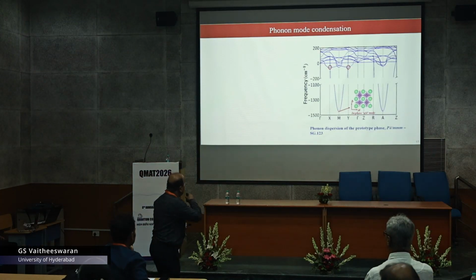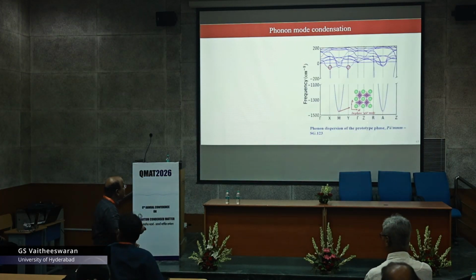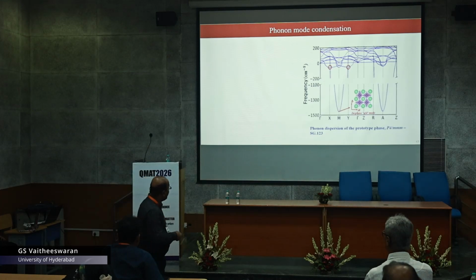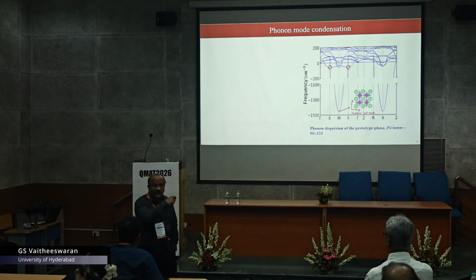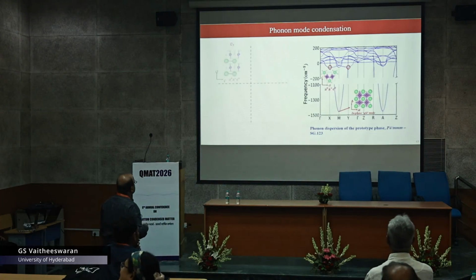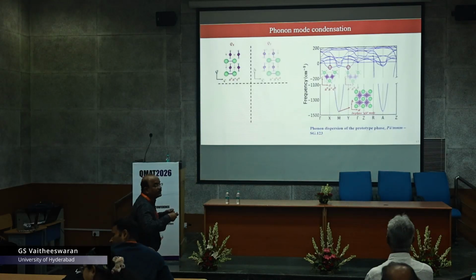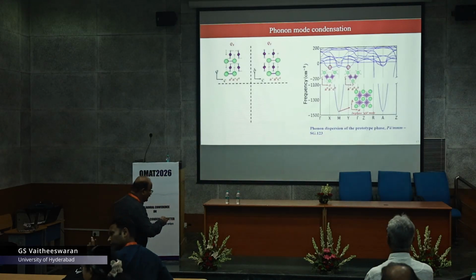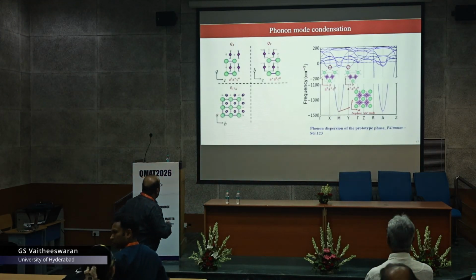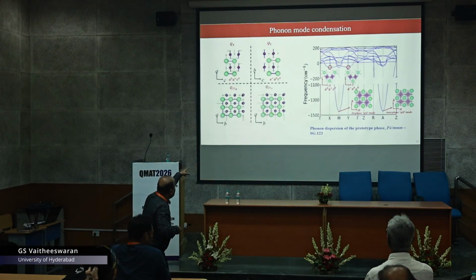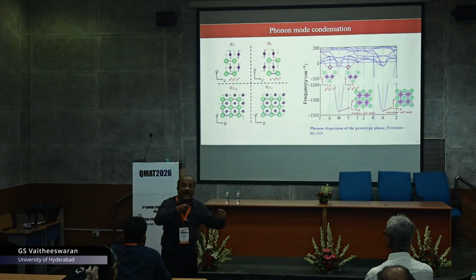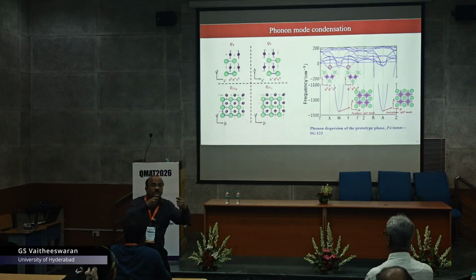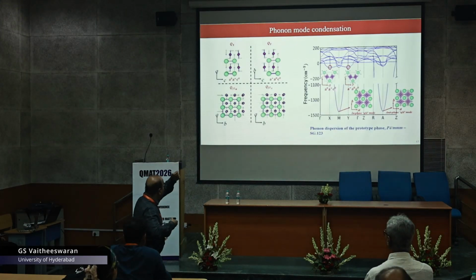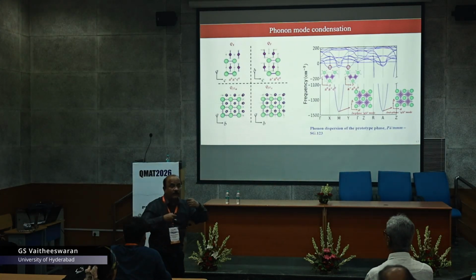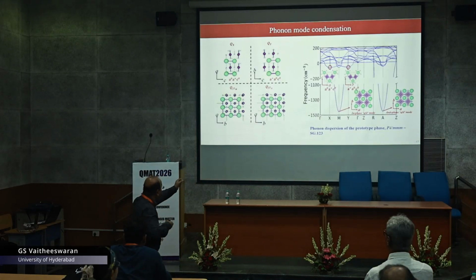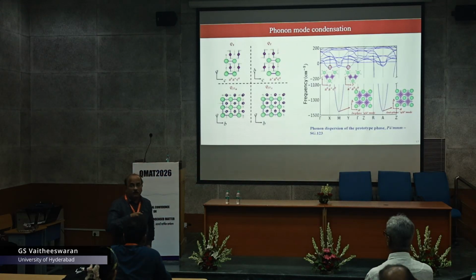Okay, so this is what we got, and we could see huge imaginary phonon modes. One is at the M point, another one is at the A point. These are the corresponding animations of the vibrations of the phonon in the particular mode, and we try to see that these modes, especially the M point and the A point, are more Jahn-Teller active. They are trying to distort that particular lattice, and we do see a Jahn-Teller kind of distortion, which is purely driven by the M mode and the A mode in the Brillouin zone.